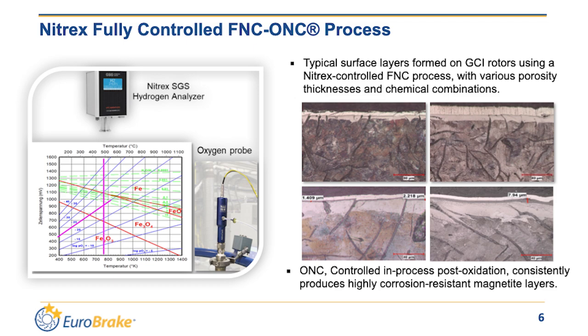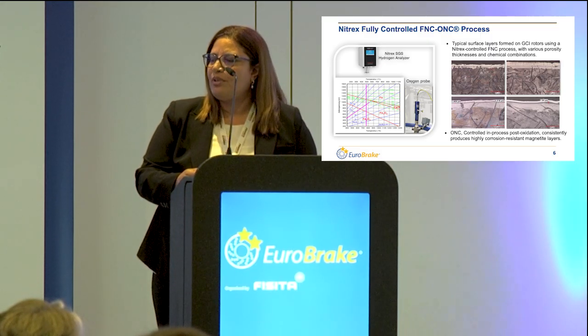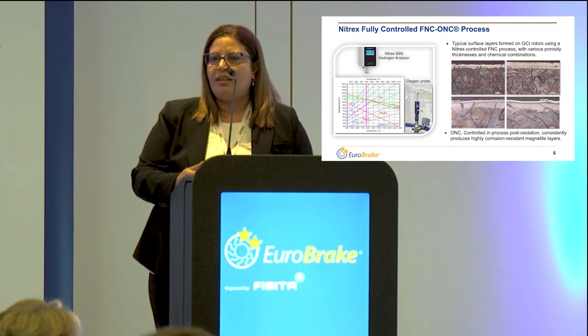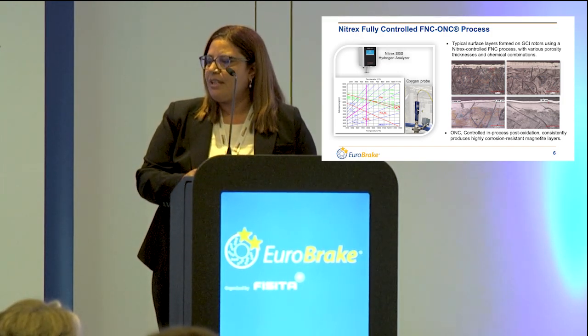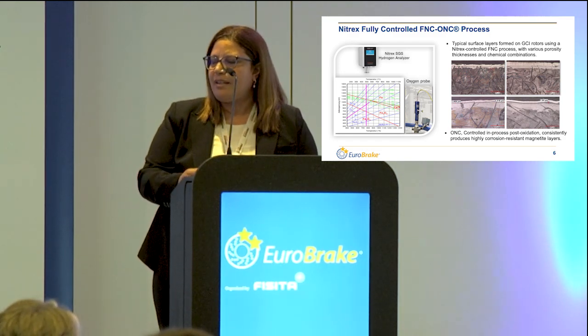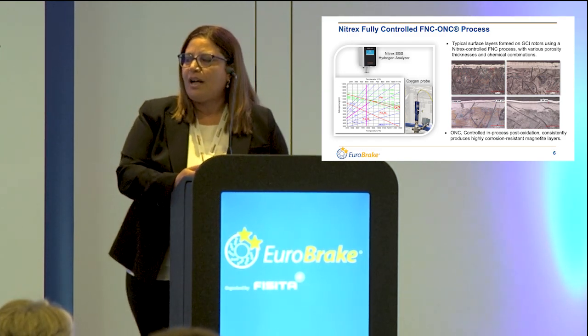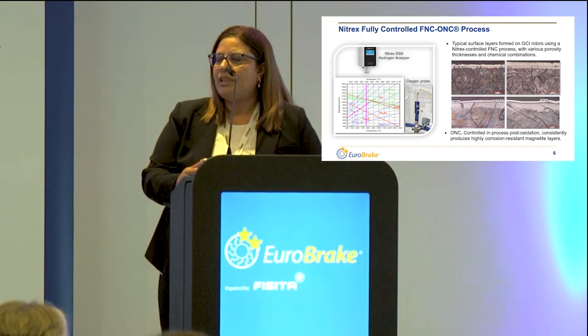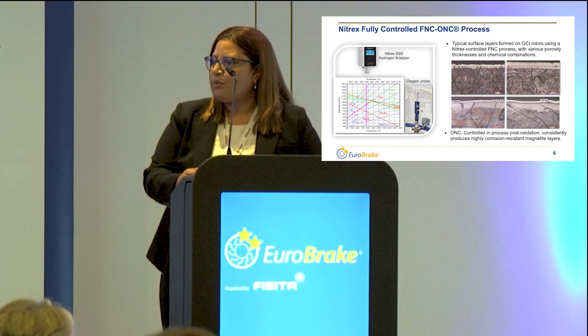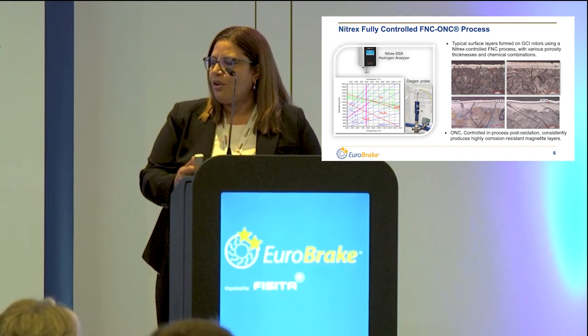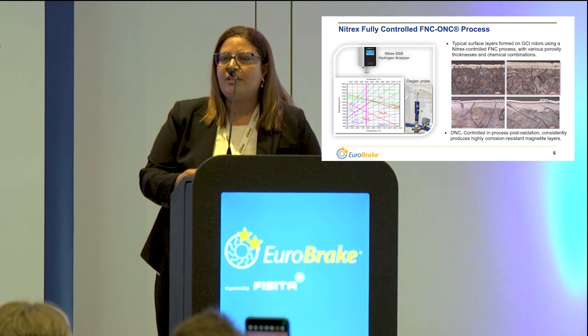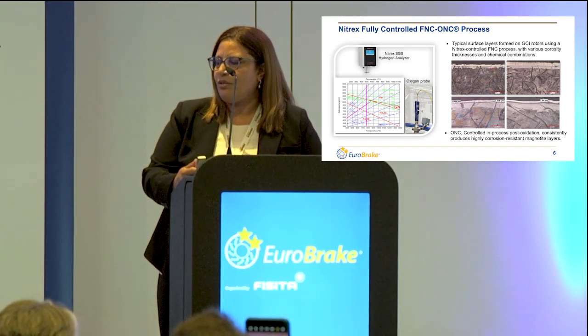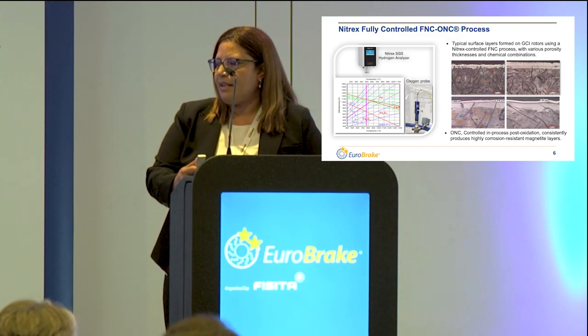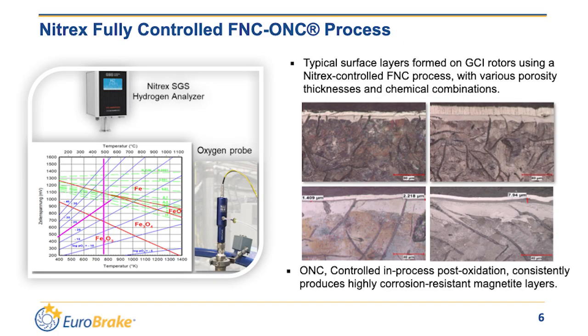The FNC treated rotors vary in their specifications from one manufacturer to another. So Nitrex has developed a new generation of FNC ONC rotors that use an advanced control system, which includes the Nitrex SGS hydrogen analyzer that allows us to obtain a compound layer with different thicknesses, chemical composition, and porosity, and an oxygen probe that allows us to control the post-oxidation to obtain the highly corrosion resistant magnetite layer. And presented here on the right are typical surfaces that we can obtain.